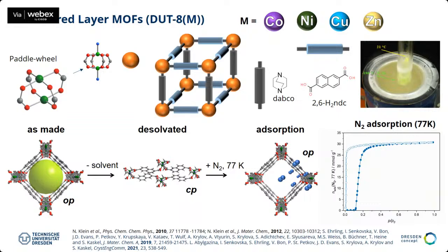This material is closed up to a certain gate pressure, but then at a certain pressure it suddenly pops open and shows a huge uptake of up to 30 millimole per gram. This would correspond to 2,000 square meters per gram surface area. So this is a typical responsive gating type of material that we discovered here. What is also very typical for this switching behavior, this opening and closing, is that you see a hysteresis in these adsorption isotherms. Whenever you see a hysteresis, it means that your material is flexible, responsive, and changes its structure. The adsorption, the uptake curve, is different in this case compared to the desorption curve.